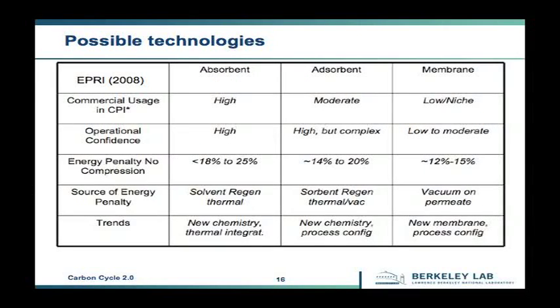And you can do some theoretical estimates, and you see with those types of technology, with the absorbents, they expect up to, say, in the 20% range. If you go to the solid adsorbents, you get up to maybe 15%, or with membranes, you get it in sort of a similar range. And these are the expectations of this parasitic energy. So you see by developing those novel materials for either membranes or adsorbents, the expectation if you would develop a process with that is actually a significant reduction.